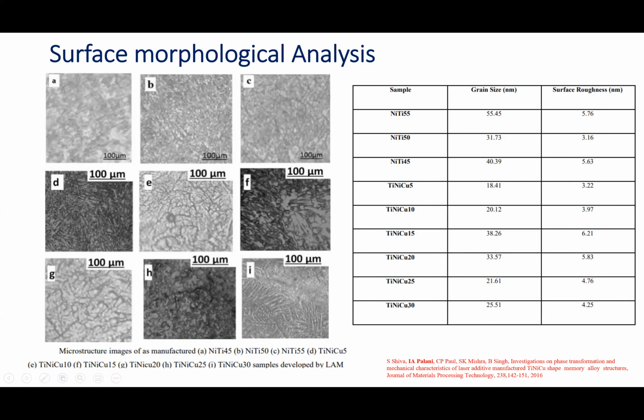Whereas in this case, if we see, this belongs to NiTi 45, this belongs to NiTi 50, this belongs to NiTi 55, and these are the combinations with respect to TiNiCu5, TiNiCu10, TiNiCu15, TiNiCu20, TiNiCu25, and TiNiCu30. Okay, so if you see, this gives us clarity with respect to the uniform and dendritic microstructure, which is due to the higher cooling rate.